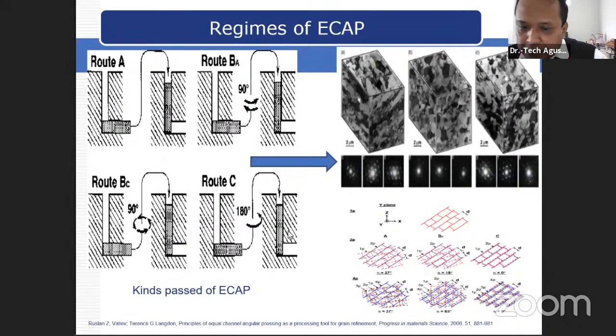During route BA, the sample is turned alternately with reverse direction, at a defined angle. In route BC, the rotation of the sample is conducted without reversing the direction, by consecutive processing at 90 degrees between each pass. In route C, the sample is rotated 180 degrees between passes. Combinations of these routes are allowed as well.